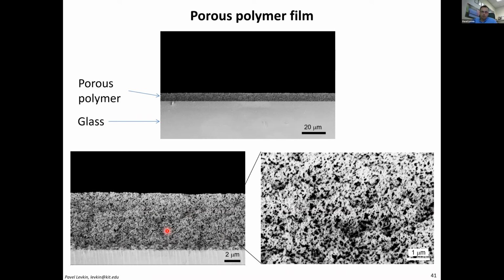And this brings me to another topic, which is superhydrophobicity. So if we take such a surface and produce it using hydrophobic monomers, for example, butyl methacrylate or even fluorinated methacrylates or acrylates, through the combination of this micro and nanostructure on the surface, the porosity, and the hydrophobic nature of the polymer, the surface becomes superhydrophobic.